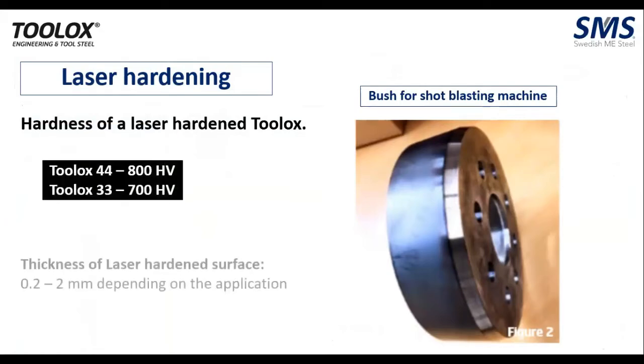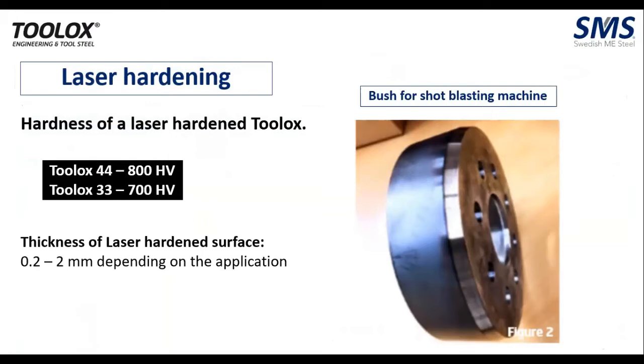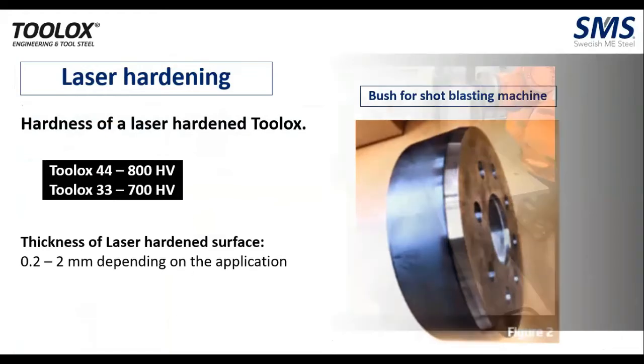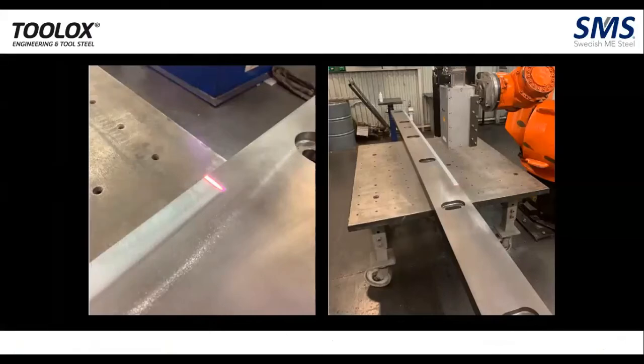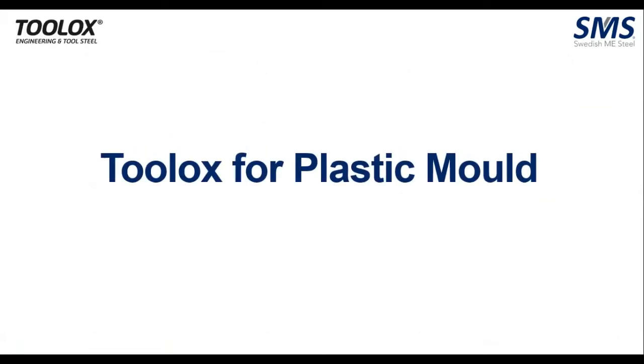Then laser hardening, as we said, is for very concentrated areas. For Toolox 44, it can go up to 800 HV, and for 33, it can go up to 700 HV. The thickness of the laser hardened surface is from 0.2 to 2 mm, depending upon the application. This is a shearing blade which has been used. So let's look at the different applications for plastic molds.